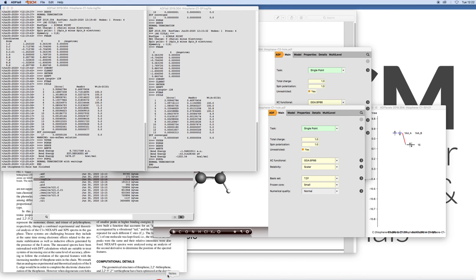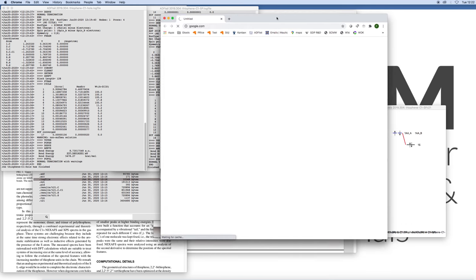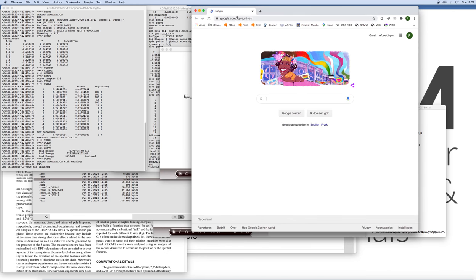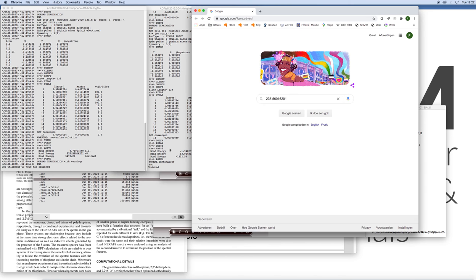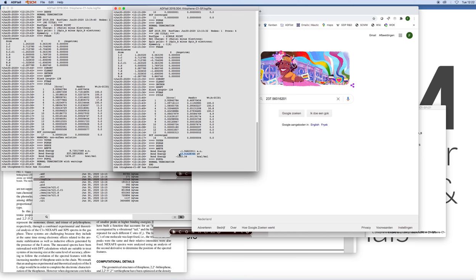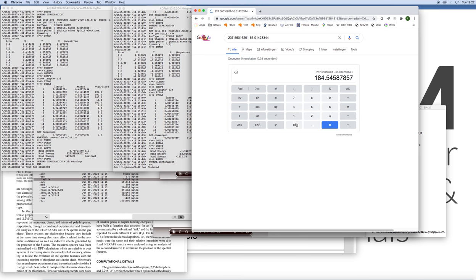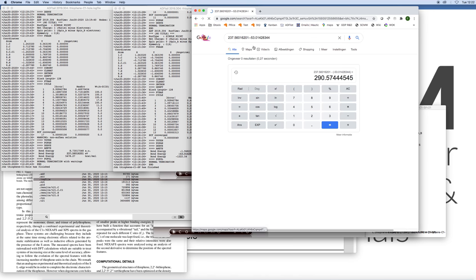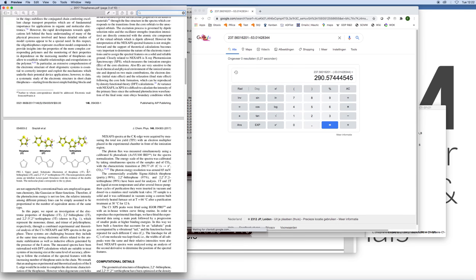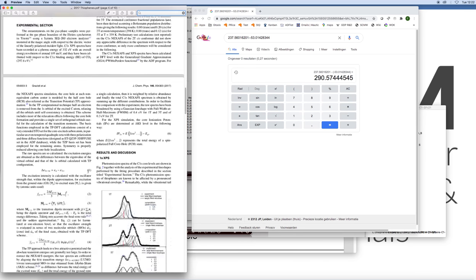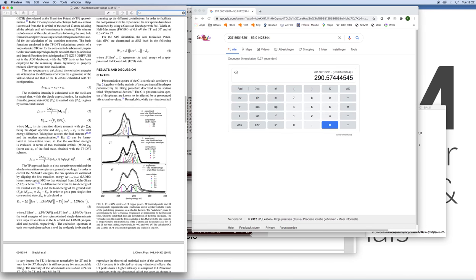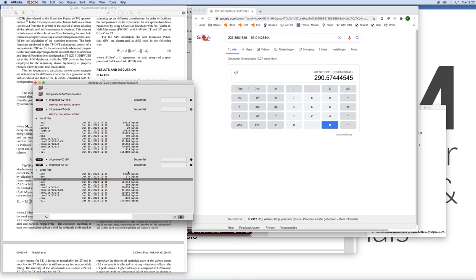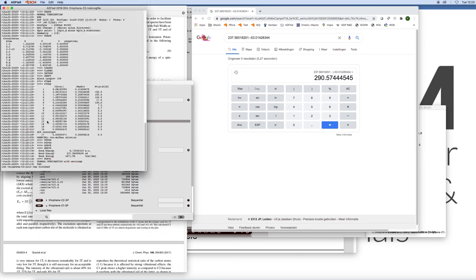Let's ask Google how much the energy difference is. 237 electron volts minus minus 53 electron volts. That should be minus minus 53. So 290.6 for carbon atom 1. Let's compare that to our spectrum calculated here. Carbon atom 1 is indeed around minus 290.6. Let's go back to ADF jobs. Let's do the same for carbon atom 2.